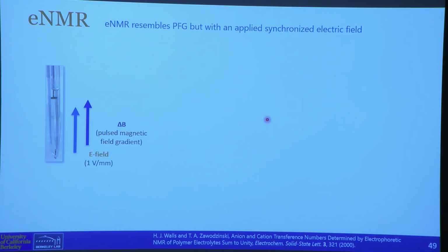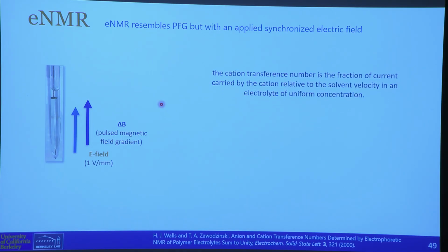So we turn to electrophoretic NMR to measure these velocities. The eNMR is just like NMR, except now you have electrodes in the tube. So we are stuck with only studying what we can put into this sort of tube. And I told you that this is the formal definition of cation transference. The cation transference number is the fraction of current carried by the cation. Usually current is carried by cation and anion, so it's the fraction carried by the cation relative to the solvent velocity in an electrolyte of uniform concentration. Every one of those words that John wrote down is precious.